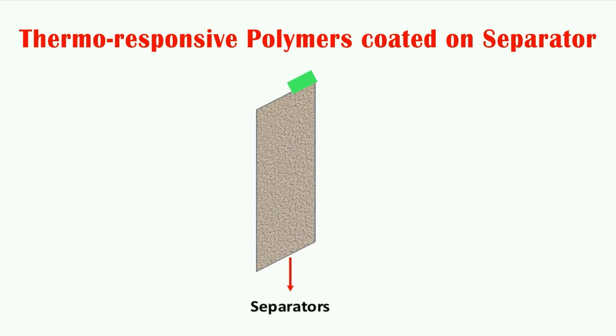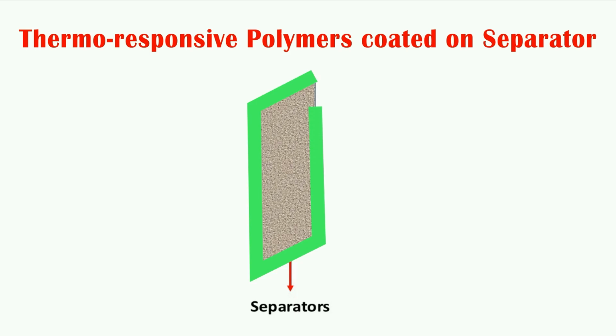Here also a thermal responsive polymer can be coated on the separator, which melts upon reaching a certain threshold temperature of the battery, blocking the pores of the separators, inhibiting the migration of the lithium ions, and thus resulting in the battery's shutdown. Thus, the use of lithium-ion batteries in the electric vehicles poses certain risks and threats, but the developments are there to avoid the same.